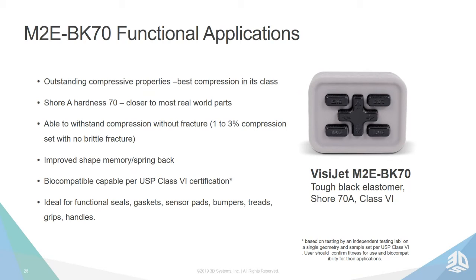What's really unique about this material is its compression set. So that's the permanent deformation that would remain after removing a strong force to the part. In this case, the permanent deformation is just 1 to 3%. Now, when you compare this to other elastomer materials that are 3D printed, it's really a world of difference. I've seen parts where we did the standard compression set test with other elastomers, and those parts totally collapsed under pressure, and they literally turned to what looks like a paste when you compress them hard.